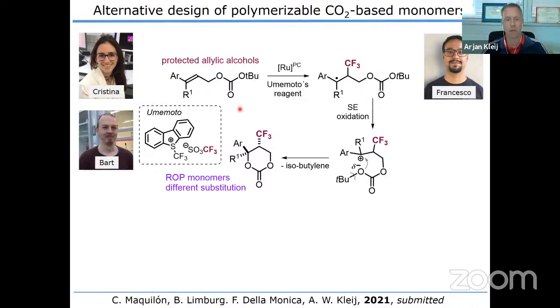with some larger diversity. So basically, the people shown on this slide, mostly Christina and Bart, in terms of the synthesis, took these allylic alcohols, so these protected allylic alcohols, which are nothing else than O-Boc derivatives, and under suitable photocatalytic conditions, you can make this benzylic radical, which you can then oxidize by a single electron oxidation, which will produce this intermediate, and this intermediate is set up to do recyclization onto that position, so this benzylic cation, expelling isobutylene, and in this way you would make a cyclic carbonate with different ring substituents. And these are potentially interesting for ring opening polymerization, and they have a different substitution, so we were very much interested to see what this substitution beholds and what kind of properties we would be able to design.